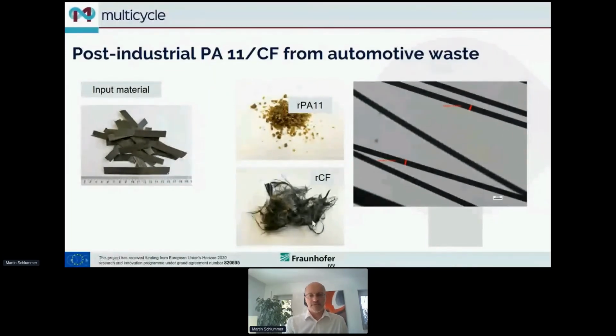The recovered carbon fibers, here you see some pictures. They also look very, very nice in terms of diameters and lengths. They are fine. The length of the carbon fibers are, of course, not endless, since the materials were chopped before we could bring them into the dissolution containers in our plant. So therefore, they are not as long as probably all of us wanted to have them, but in the end, good enough to get some checks.